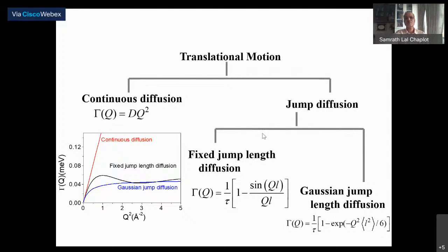Of course, you also have inelastic scattering because of vibrations at times which are less than tau, for example. When the atom is still resident where it is, there can be vibrations that give you inelastic scattering. But over longer times, you have diffusion, and so the half-width at half maximum of the Lorentzian function has information about the jump dynamics, for example, the jump length.